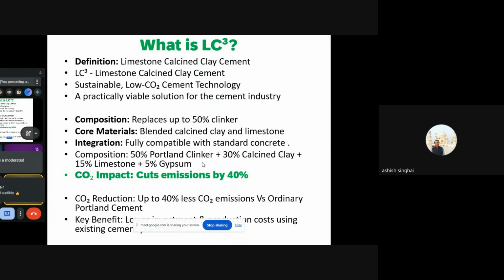So what it is, how it is made, its composition. First and foremost, 50% clinker is replaced. All of us know that clinker is a product which is calcined to the extent of 1450 degrees Celsius. That powdered form of limestone gets in a flowable form. It melts, it flows, then it is quenched rapidly. So it becomes granular, what we call clinkers. These clinkers are then ground to fine powder, and fly ash and gypsum powder are added with this composition, and that is how we get cement.